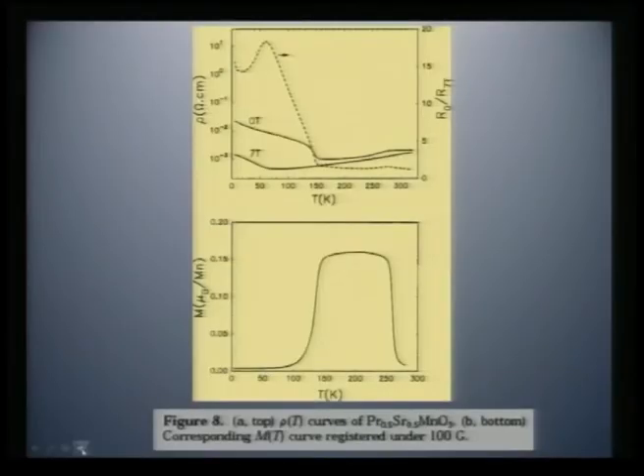This is another very interesting case where you see praseodymium is in a charge ordered state, because you have substituted up to 0.5. Therefore, this is a charge ordered situation where this is your ferromagnetic transition and this is your antiferromagnetic transition. So, from a paramagnetic it goes to a ferromagnetic transition and then it comes to an antiferromagnetic transition. This is clearly seen because if you do the resistivity versus temperature plot, up to this place it is more or less a weakly metallic state and then immediately it goes to an insulating state. At the Néel temperature there is also an insulating phase.